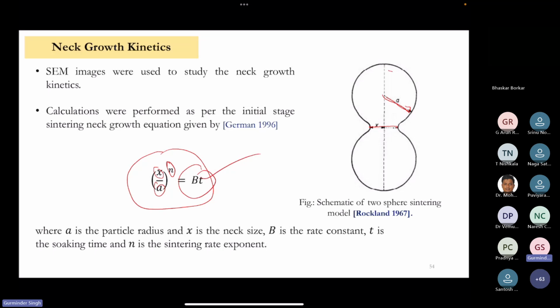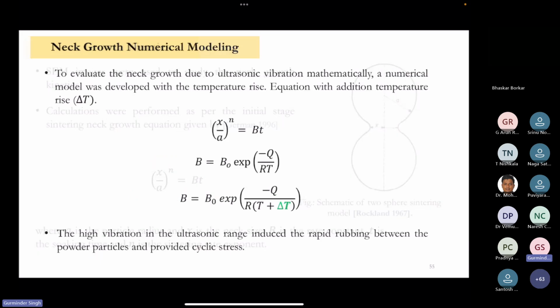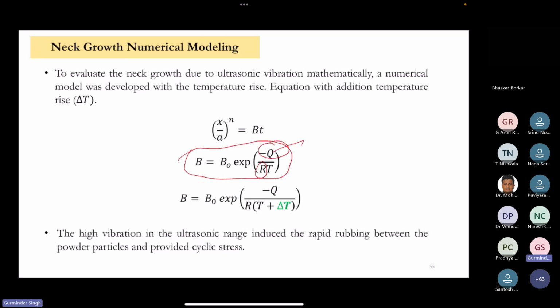Here t is your soaking time, meaning your sintering time, or up to what time you have kept it for sintering. And B depends upon your activation energy and the gas constant. Activation energy is the energy required for the sintering. It depends on the material, and it has the temperature T. This is your sintering temperature. So we have chosen this model.